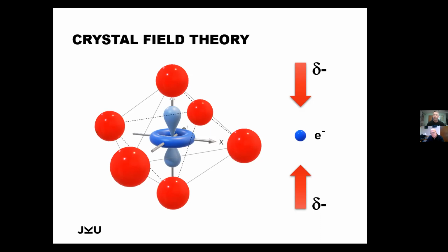And this is, for example, a simple explanation why chromium in some minerals appears red, and in some others, like in emerald, it appears green, because the crystal field is different. The crystal symmetry, the oxygen atoms that are neighboring our chromium, are pressing harder or less hard onto the electron shells, and therefore we have different absorption levels and different absorption colors.